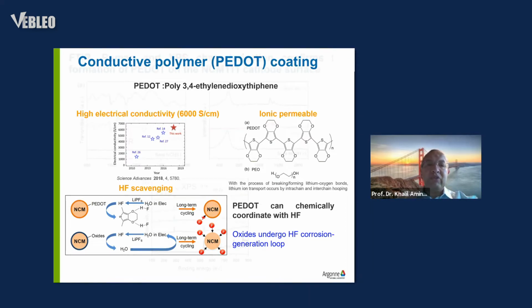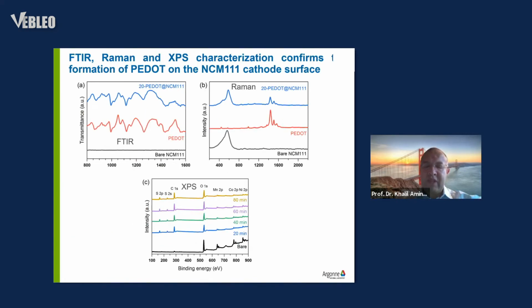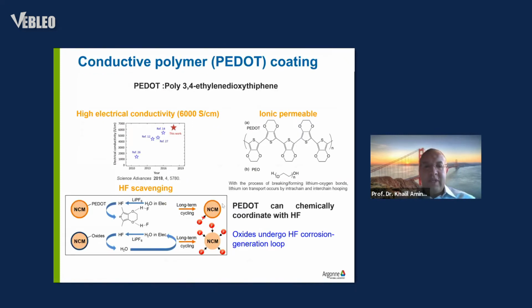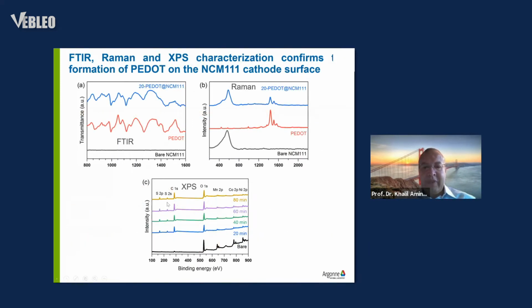So the first thing we need to do is to confirm that we have a PEDOT coating. We confirmed that by three techniques: FTIR, Raman, and XPS, which, as you know, is a surface technique. What we want to do is to probe, for example, the main component of the PEDOT, which is sulfur, as you can see here. You can see clearly that when you start coating, depending on the time, sulfur peaks are formed that do not exist in the initial bare material.